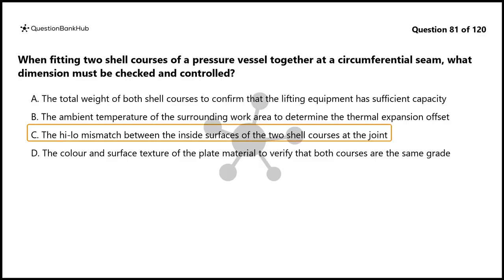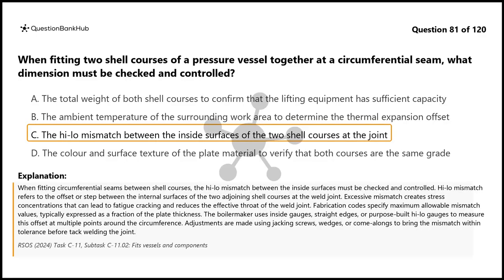The correct answer is C. When fitting circumferential seams between shell courses, the high-low mismatch between the inside surfaces must be checked and controlled. High-low mismatch refers to the offset or step between the internal surfaces of the two adjoining shell courses at the weld joint. Excessive mismatch creates stress concentrations that can lead to fatigue cracking and reduces the effective throat of the weld joint. Fabrication codes specify maximum allowable mismatch values, typically expressed as a fraction of the plate thickness.